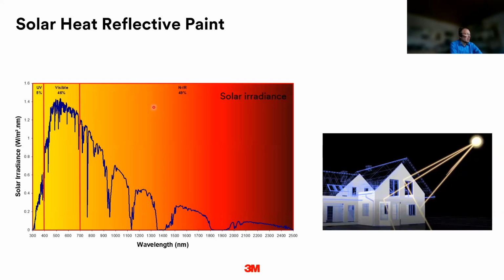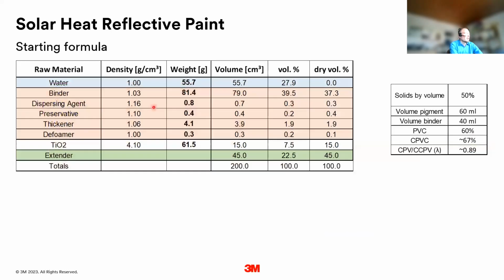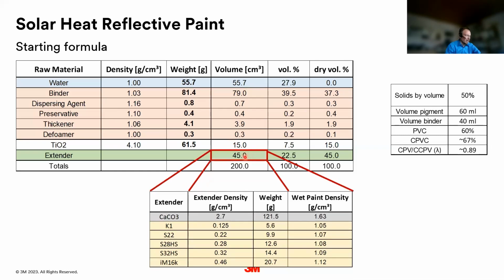So, in the next slides, I would like to show you what glass bubbles can do to improve reflectivity of paints. And for that, we did a small study starting with a very simple paint formulation. And for this paint, basically everything was kept constant: water, binder, all the additives, titanium dioxide. And we always used the same amount of filler in terms of volume. But we used different fillers. So we prepared four different paints with different fillers.